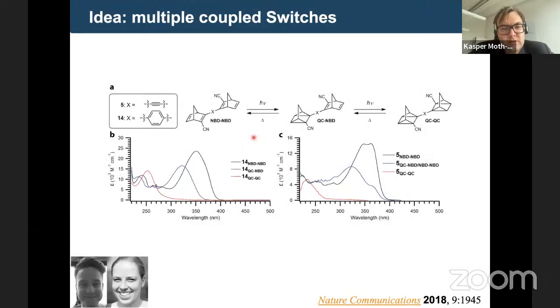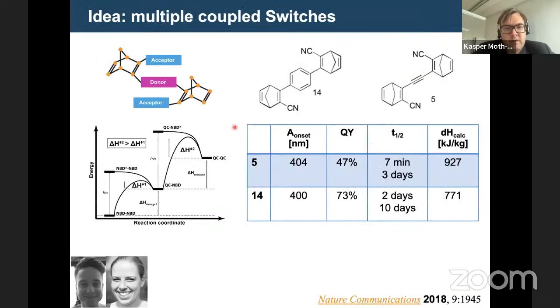So we went and made the molecules, and here you see the optical properties, how they look for the norbornadiene, singly switched and double switched. So you see there's a very big optical change in these molecules, and there are different variations with phenyl and acetylene spacer groups in the middle. But what is also interesting is the half-life, the time it takes for it to go back. For this one here, the first switch goes back in 7 minutes, but if we switch it 2 times, then it takes 3 days before it goes back. And this one is 2 days for the first one and 10 days for the second one. So the coupling here is a little bit weaker between the systems, but still conceptually it works.